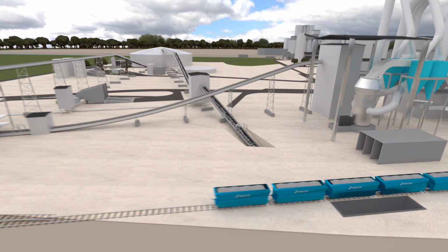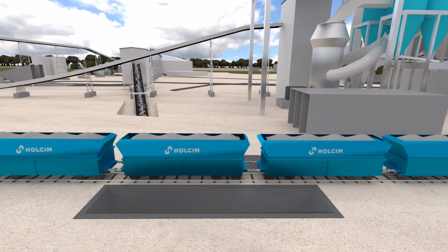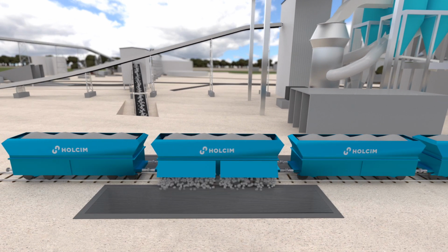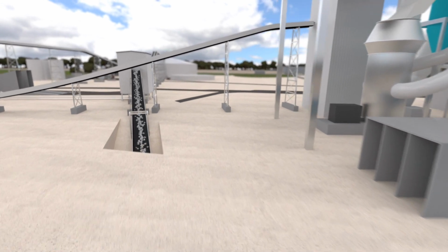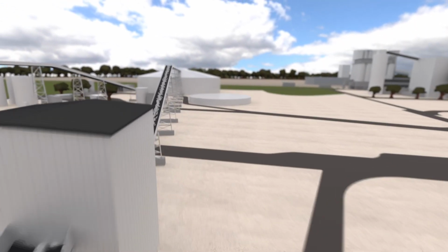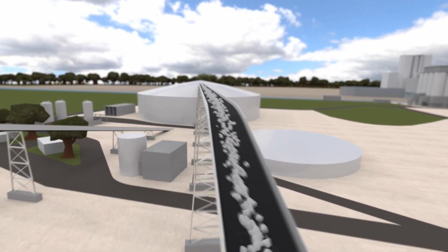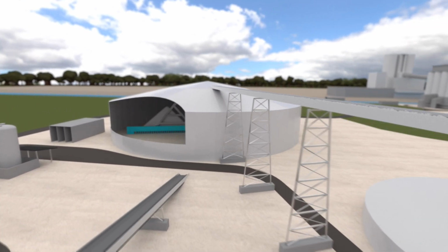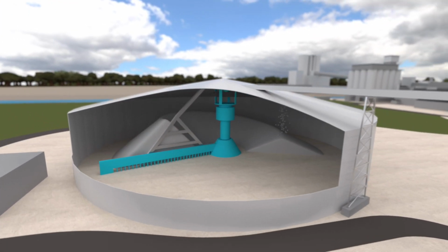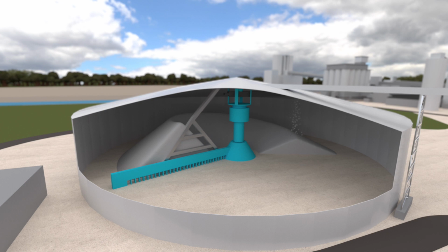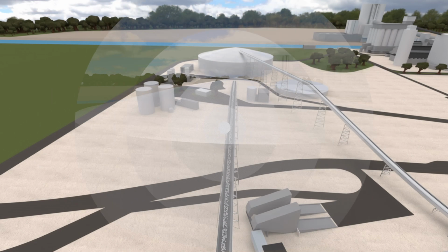On arrival at the Obourg cement plant, the limestone is automatically unloaded into a hopper and transported by conveyor belt to the pre-homogenization hall. The hall is filled in a circular manner, and the materials are reclaimed transversely by a scraper. This method makes it possible to obtain better consistency in the chemical composition of the mixture, which comes from the various geological layers of the quarry.